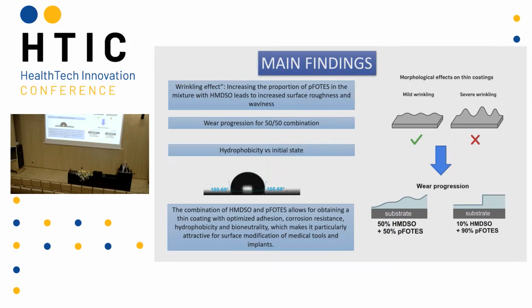We also performed a huge number of studies for these coatings, but these are the main findings. We observed the wrinkling effect: increasing the proportion of PFOTES in the mixture of HMDSO leads to increased surface roughness and waviness. We can also observe wear progression starting from the combination 50 to 50 onwards. And we achieved the hydrophobicity versus initial states.